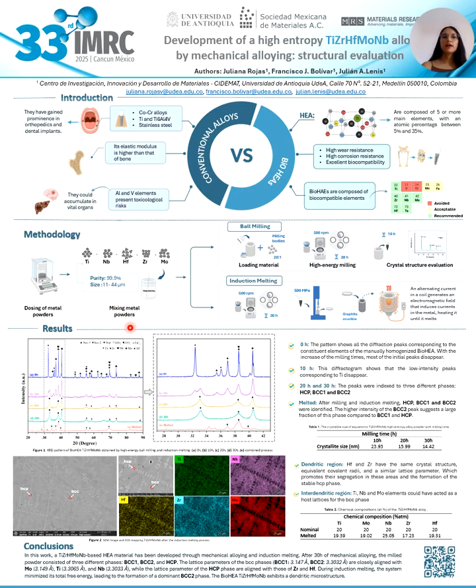These powders have different morphologies, including irregular shapes and spherical agglomerates with particle size ranging from 11 to 44 micrometers. For the milling process, the powder mixture was deposited into the pot in a ball to powder ratio of 20:1. All this process was carried out in controlled atmospheric conditions to avoid oxidation. Subsequently, the milling process was performed for 30 hours at 500 rpm.